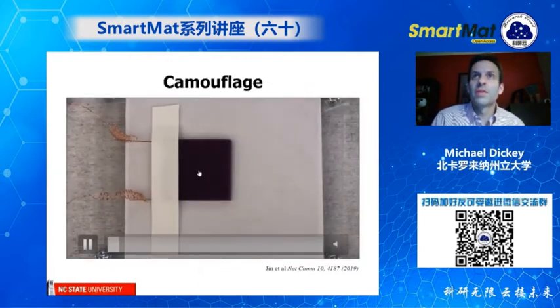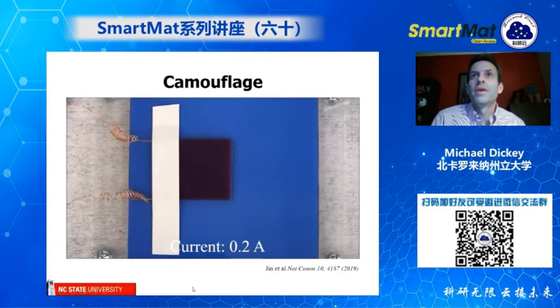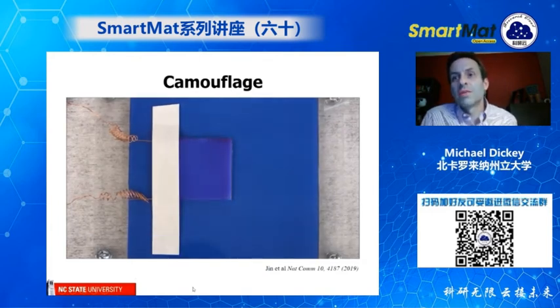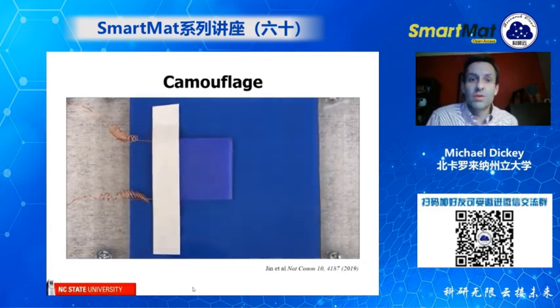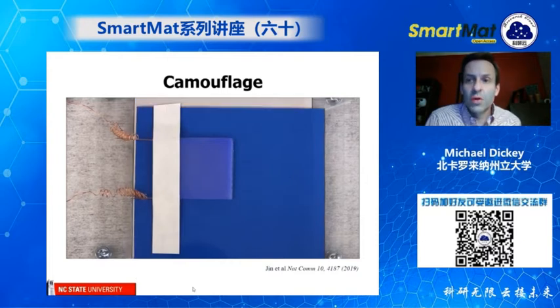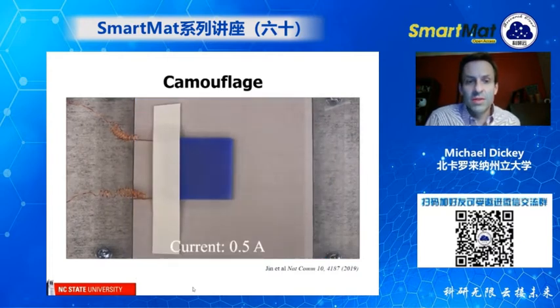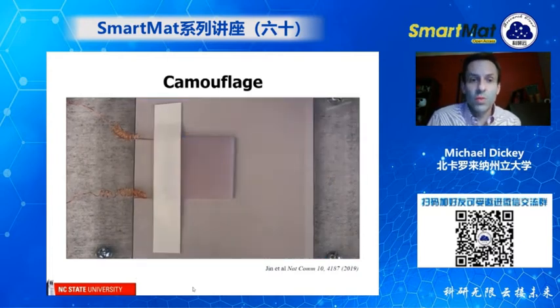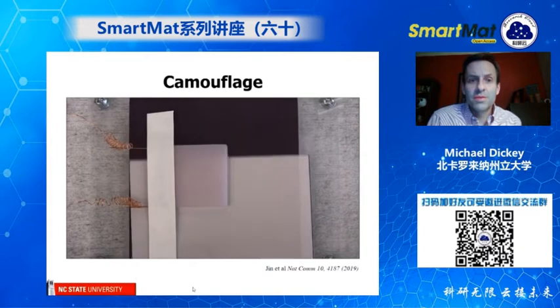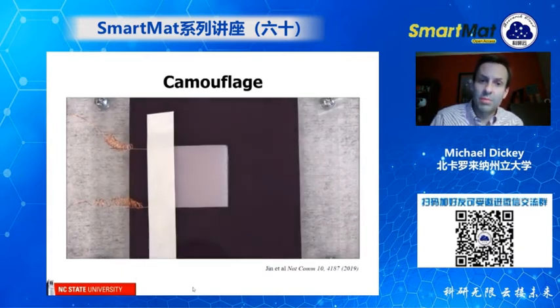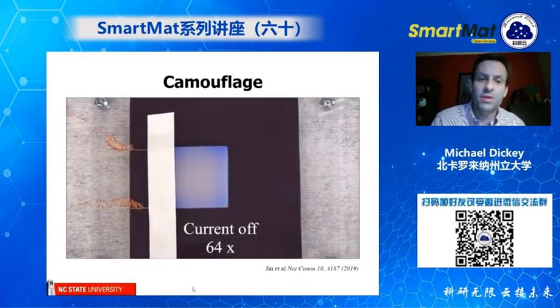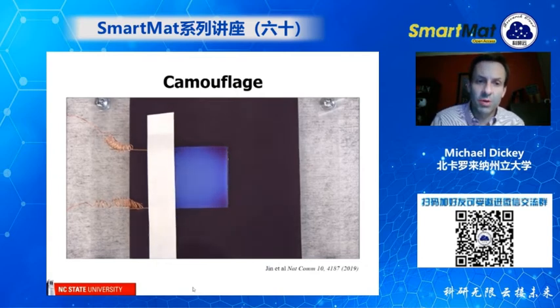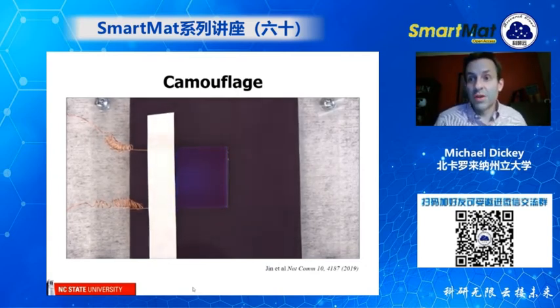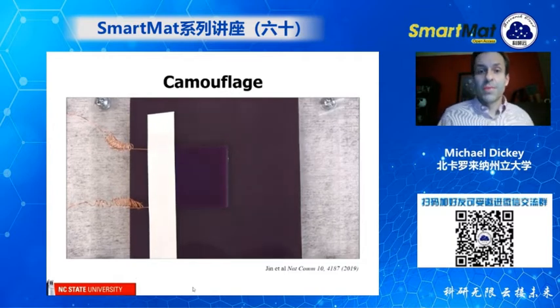And the red and the blue pigment actually change at different temperatures. So if you mix the red and the blue, you get purple. If you run a little bit of electricity, the red disappears and you get blue. If you run more electricity through this device, the blue disappears and you get white. And so then if you let it cool back down, the pigments go back to the original color. So they'll go back first blue, and then the red comes back and it appears purple. So this looks very nice, but I would say sort of obvious.